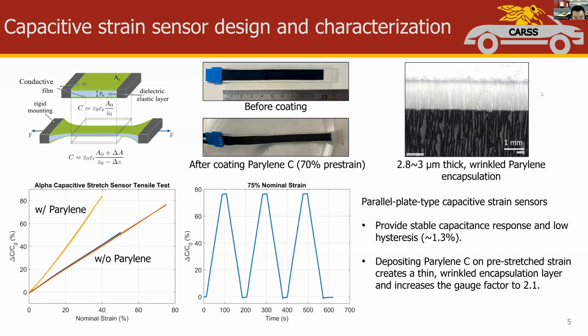Since the wrinkle structure can allow the sensor to maintain a constant width during stretching process, it actually increased the sensor's gauge factor from 1 to 2.1, which made our strain sensors even more sensitive to strain.